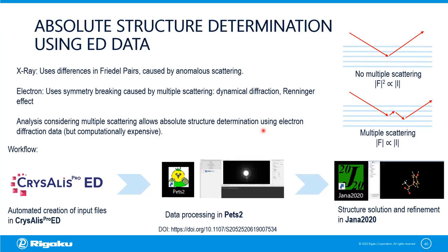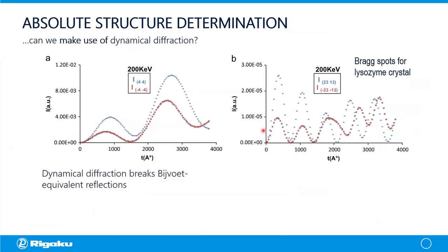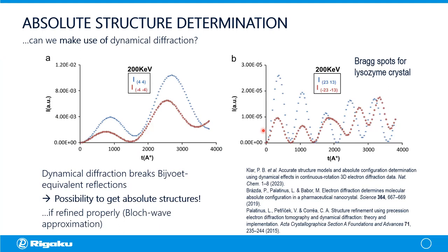So this is done using CrysAlisPro ED. We create a set of input files that can be taken into PETS. Then PETS can do the dynamical refinement, create files for Jana2020, and then we can do structure solution and refinement in Jana2020. So what happens? Well, in absolute structure determination in electron diffraction, we actually use the dynamical diffraction effects, which break the equivalency of Bijvoet pairs and make it possible to get absolute structures. One has to do the refinement properly.